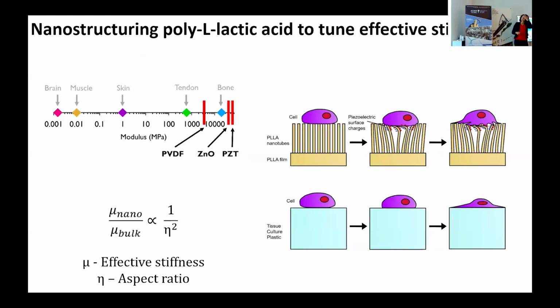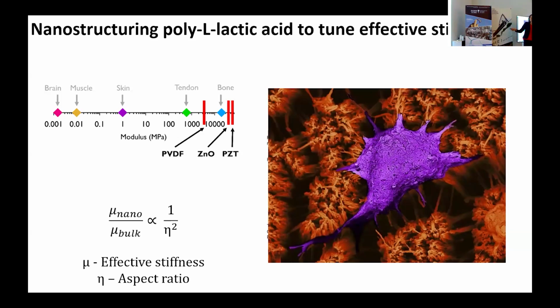And we can harness this because you can use nanostructuring as a tool to tune the effective stiffness. If you look at the body, you've got all ranges of stiffnesses, from brain all the way to bone, whereas most of the experiments we do are in tissue culture plastic with one set stiffness. Even if we were to replace these with piezoelectric materials, these are still at the stiffer end. However, you can change the stiffness. This is a nice engineering trick by nanostructuring. If you have structures with long enough aspect ratios, the effective stiffness actually goes as the inverse square of the aspect ratio. So basically, the longer and more slender they are, the bendier they are. We can use this to tune the mechanical environment for the same material, keeping everything else the same, crystallinity, surface potential, etc., to see what effect this might have.